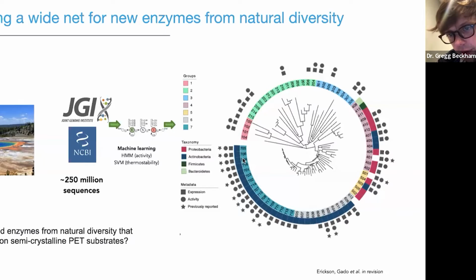And what you can see is if you look at clades, these are different clades. So clade 1 through clade 7 around this circle. Clades 7, 6, and 5 had enzymes that were previously reported. All of the enzymes like Ideonella, leaf compost cutinase, T. fusca are all over here in clade 6 and 7. But once you get out here into clade 4, clade 3, clade 2, and clade 1, none of these have ever been reported before. And you can see from this phylogenetic tree that the diversity, once you get out to clade 4, is quite substantially different than clade 7, which is all very closely related, and clade 6, which is still very, very close phylogenetically.